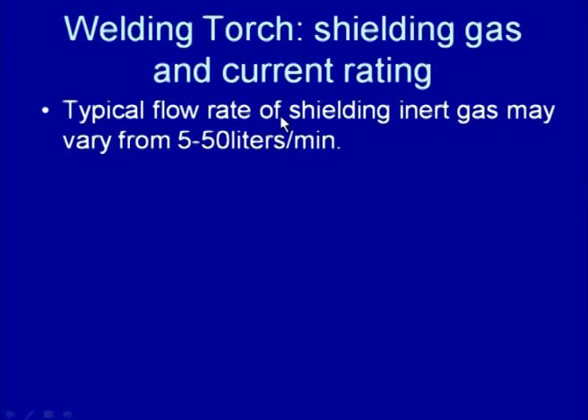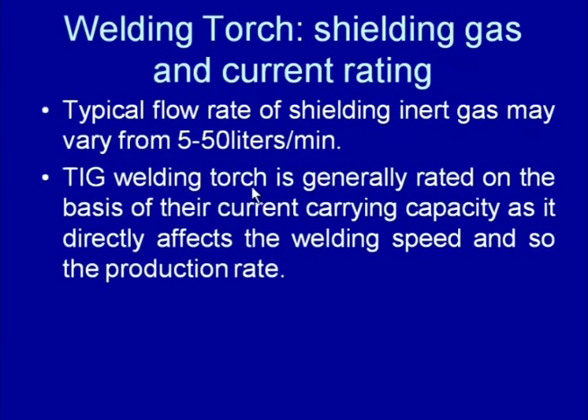Now, we will see that a variety of shielding gases are used, and they are allowed to flow at different rates during welding. What are the factors that affect the selection of the shielding gases, and how do these things affect the way a sound weld joint is obtained? The shielding gas flow rate can vary significantly from 5 to 50 liters per minute. What should the flow rate be? That is governed by the diameter of the electrode, the nozzle size, the speed at which we are moving the arc during welding, and the extent of protection desired. Depending upon this flow rate, we can have ineffective or effective shielding.